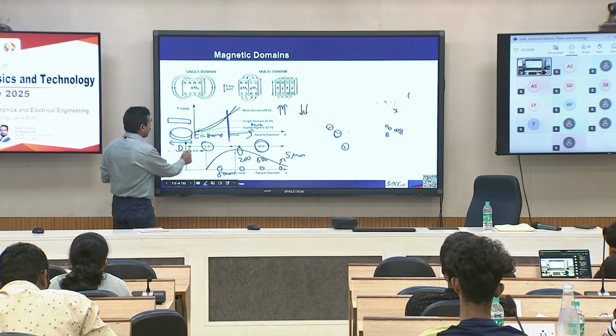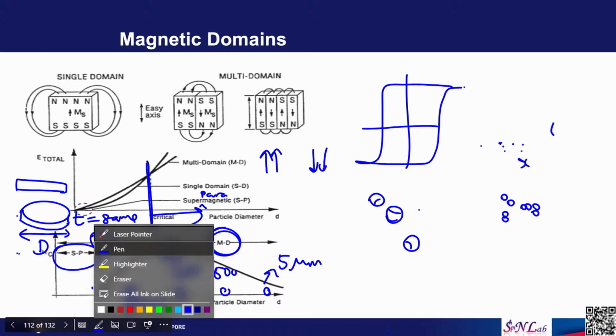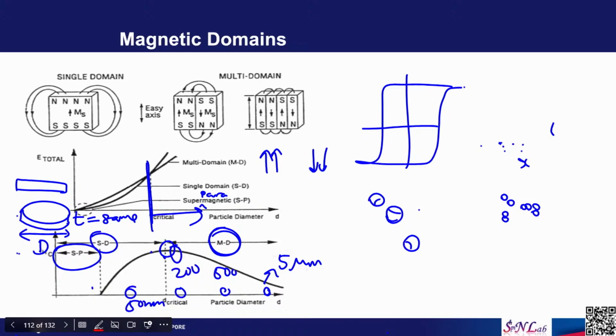So, when you are in the super paramagnetic region, the particle will not have coercivity, okay, because they are fluctuating as a function of time. The hysteresis loop will vanish. So, normal case, let us say you measure the hysteresis loop here, you will have coercivity like this, but if the particle size is too small, then there is no hysteresis loop, the curve will be like this.